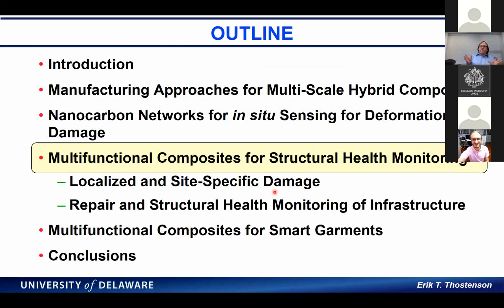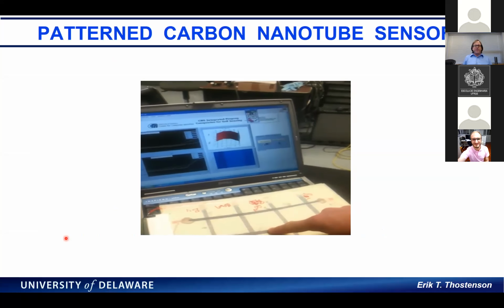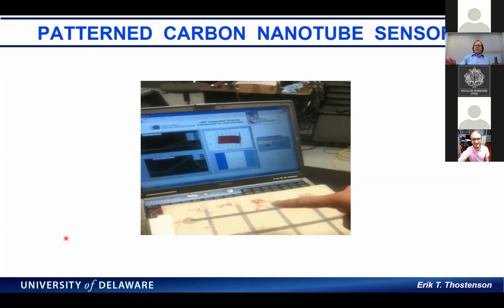So this is a video I just wanted to show. This was just something an undergraduate student had done many years ago, where he made this panel and we tailored it and we integrated the carbon nanotube network in a patterned way. And what you can see, that's actually me pulling on it, and we'll let it replay again. So you see where I push on it, you see in the background the curvature of the plate. And then also where I grab on the corner, you also see that corner of the plate lift up on the screen. So that was something where we could say, well, we can use these as distributed sensors in a structure in order to not only measure cracks, but we can also measure the deformation.